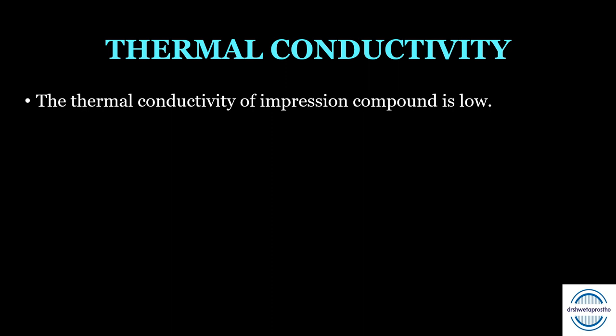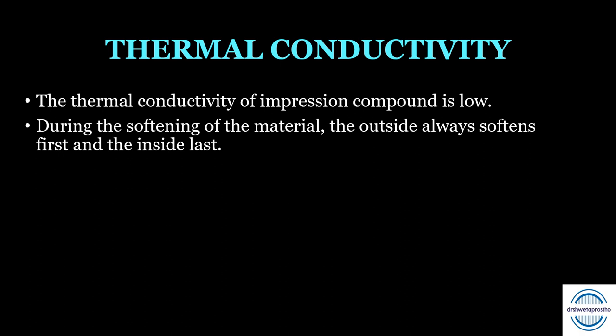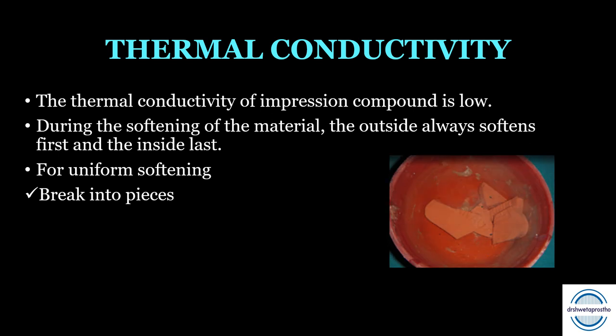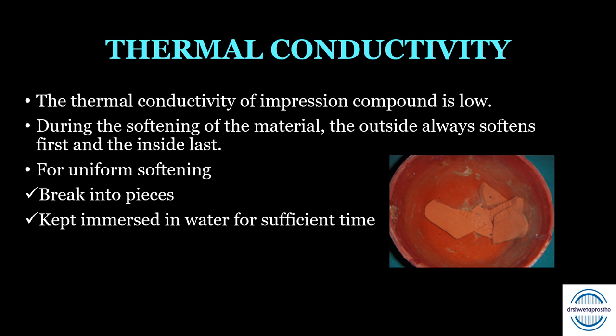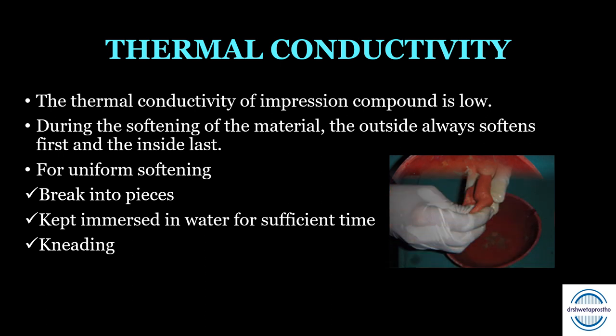The thermal conductivity of impression compound is very low — it is a poor conductor of heat. During softening, the outside part softens first and the inside last. To ensure uniform softening: first, break it into pieces before placing in the water bath; second, keep it immersed in hot water for a sufficient period; third, kneading is very essential as it ensures uniform softening has taken place.